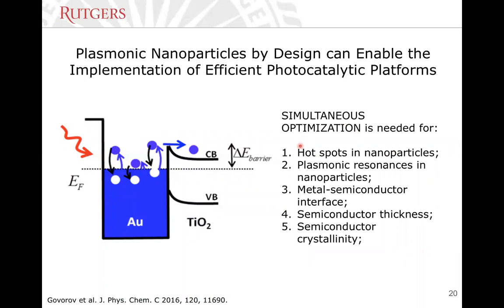However, to do that, we have to really follow these design rules. We need to obviously create the hot spots, create the hot electrons. We need to tune the resonances to be in the near infrared. We have to optimize the metal semiconductor interface to reduce to a minimum any defects, to remove any capping agent, because that would really hinder the transfer of the electron. We have to create a semiconductor that is crystalline, but is also very thin, so that any hot electron that is extracted into the TiO2 can be further extracted into the surrounding environment where it can run reactions, in our case, in the surrounding water.